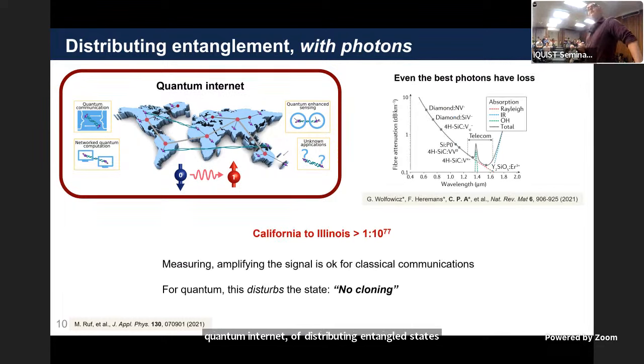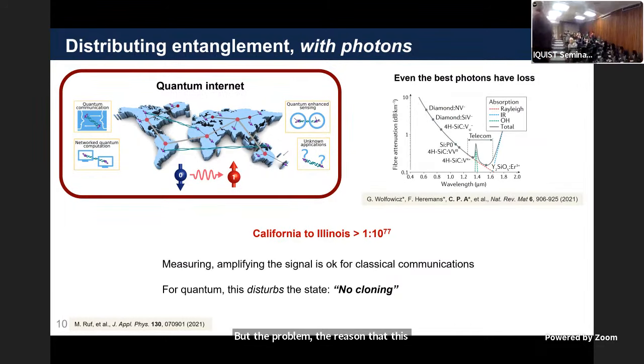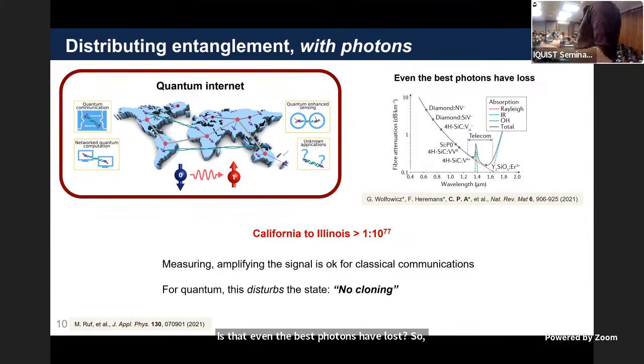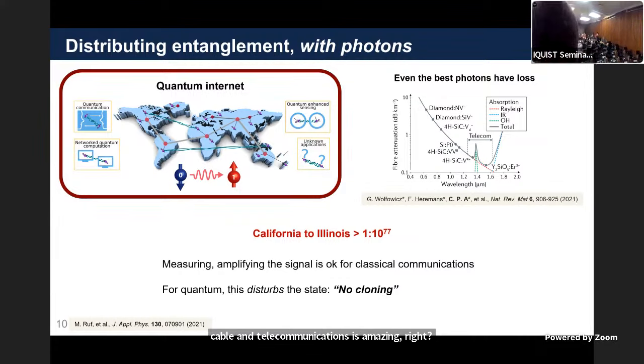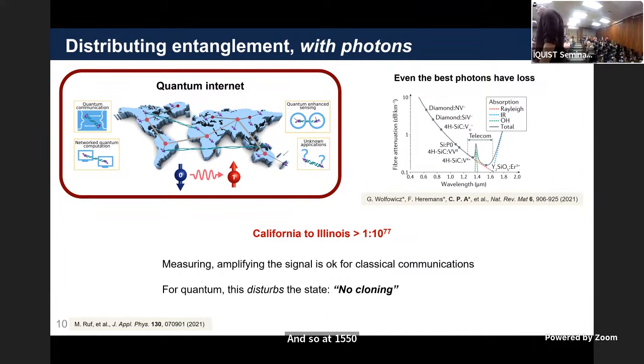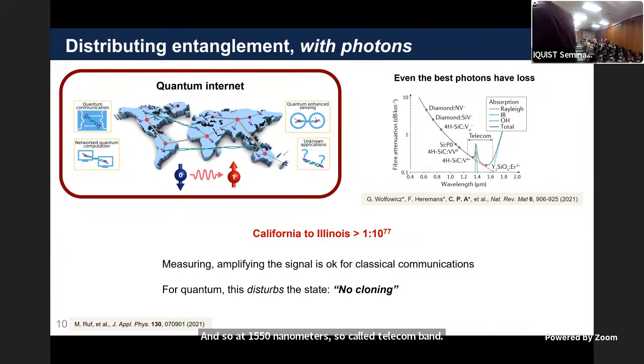But the reason that this dream isn't everywhere today, the reason that this is still a science and engineering problem, is that even the best photons have loss. So fiber optic cable and telecommunications is amazing, right? Super low loss, great technology, but it's not zero loss. And at 1550 nanometers, the so-called telecom band, you have something like 0.2 dB per kilometer of loss, which if you're an engineer means something, but if you're not familiar with dBs, that's maybe a little bit harder to deal with.